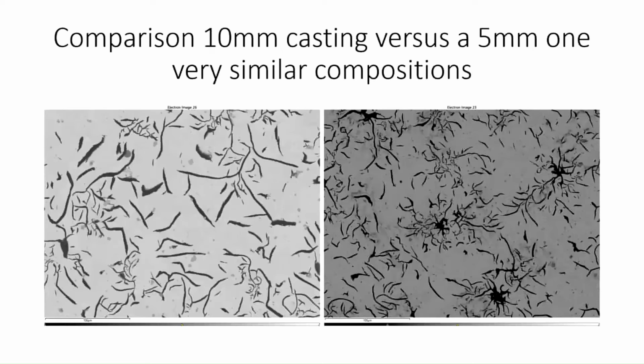The second phenomenon is that if you cast a thick casting with a composition that was meant for a thin casting, your graphite flakes would be very large. Here I just happen to have these analyses in my collection. The right-hand one is from a 5mm casting. The left-hand one is from a 10mm casting, and you can see the graphite flakes in the 10mm casting are much thicker, much bigger than the 5mm. If you cast those into a 20mm casting, the graphite flakes will be very large, and the graphite flakes are, of course, a pathway for cracks to develop throughout the material. So to get the very strongest casting, you wanted an iron that was just grey, that had the smallest flakes that you could get.